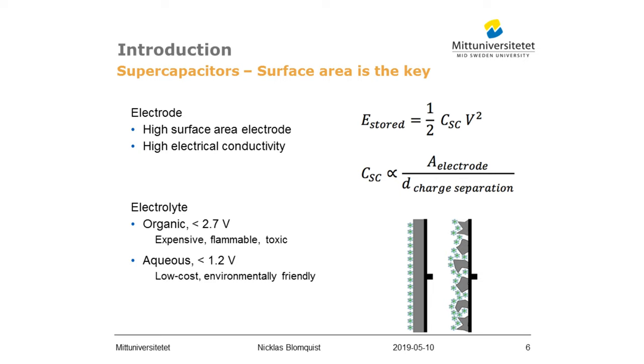If we then have a solid electrode, like this, only the outer surface contributes to this capacitance. But if we have a porous electrode, we have more surface area, we can get more ions close to the surface, and we get a higher capacitance. So high surface area is the key to store energy in a supercapacitor.